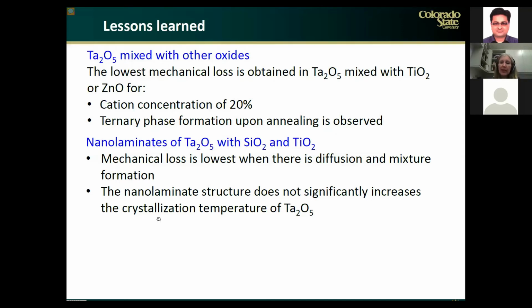Now, the results on the nanolaminate showed that the nanolaminates do not give us a significantly different behavior than the mixtures in terms of mechanical loss, because we obtain the lowest mechanical loss when there is diffusion and mixture formation. But what we learned is that not all nanolaminates are robust and stay intact to high temperature annealing. Rather, there are some in which there is diffusion and mixture formation.